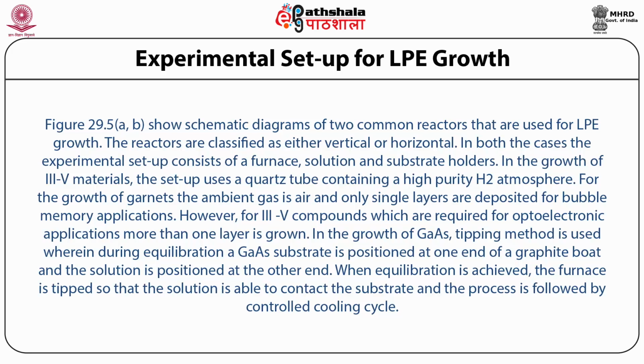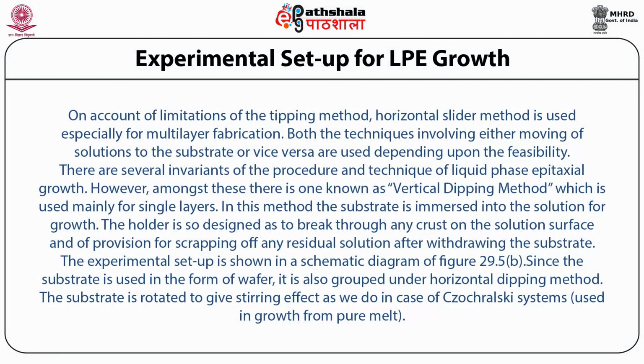In the growth of gallium arsenide, the tipping method is used, wherein during equilibration, a gallium arsenide substrate is positioned at one end of a graphite boat and the solution is positioned at the other end. When equilibration is achieved, the furnace is tipped so that the solution is able to contact the substrate, and the process is followed by a controlled cooling cycle. On account of limitations of the tipping method, the horizontal slider method is used, especially for multi-layer fabrication. Both techniques, involving either moving the solutions to the substrate or vice versa, are used depending upon the feasibility.